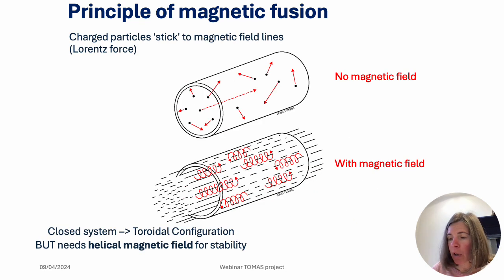When you then apply a magnetic field to these particles, they will start to follow the magnetic field lines because they are charged, and there is a Lorentz force that will force them to make a gyration around magnetic field lines. You can see for the cylinder, in the straight part of the cylinder, the particles do not escape anymore, so they nicely follow your field lines. They are what we call confined. But of course, the edges still have a problem because there you will lose your particles. So a straight cylinder is not a good solution, but it is a starting point.